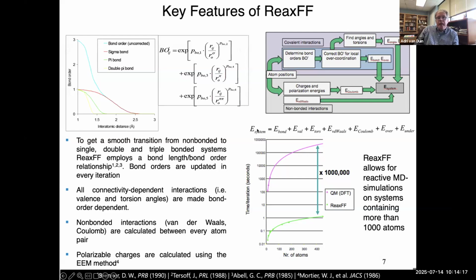So we separate the system charges into various independent charge contributions. And the reason why we do this: ReaxFF is not more accurate than DFT. It can approach density functional theory accuracy reasonably well, but it's always going to be less transferable, but it is much, much faster. And also ReaxFF is much faster than most neural network-based potentials, with some exclusions here and there.